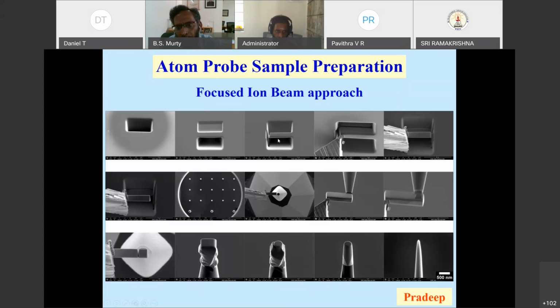And then what you do is take a needle or a sample holder, which we weld it to this. Everything is being done inside the SEM. Please understand this. This welding is done by depositing platinum at the junction between the two, and then you cut the second side so that you are basically lifting a sample like this. Once you lift the sample, bring it and put it onto a micro pillar, and then again join these ends with again a platinum.